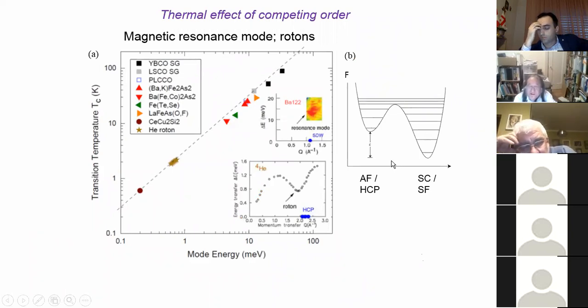So the effect of this competing state can be seen by performing neutron scattering experiments, or by noticing that in all these newer superconductors, there's some inelastic excitation measured by neutron scattering called the magnetic resonance mode. And that magnetic resonance mode is related to TC linearly. Okay, and so it seems that this excitation mode is important for determining the superconducting transition temperature of these unconventional cuprate and other systems. It's not only cuprates, but as you can see, universally, this relationship is holding.